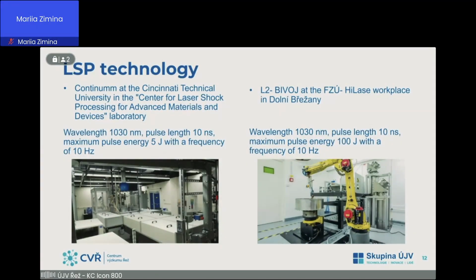Okay, we used two technology and two LSP station for our experiment. The first and mainly is LSP station in Hilase with L2 Bivoj laser system, with wavelength 1030 nanometers, pulse length 10 nanoseconds, maximum pulse energy 100 joules. It's a very powerful laser with a frequency of 10 Hz. And the second LSP station is Continuum at the Cincinnati Technical University, a Center for Laser Shock Processing for Advanced Materials and Devices.